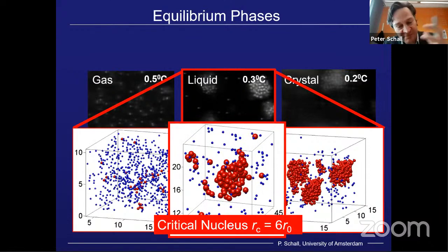And just to give you a nice picture and example, we could determine the critical nucleus, what it looks like, how it fluctuates. We could even measure from these fluctuations the surface tension, the effective surface tension of this created nucleus, which in fact is not trivial. There's quite a discussion in the literature, if you look into papers, about what this surface tension, I mean, for real atomic liquid is. And the discussion evolves around that. Of course, you know it for a flat surface. If you have a macroscopic, let's say, surface which is flat, you know what the interface tension is, you can measure it.